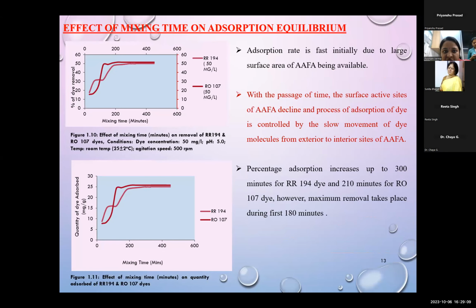Effect of mixing time on adsorption equilibrium. As we can say from both the graphs, the adsorption rate is fast initially due to the large surface area of AAFA being available. With the passage of time, the surface active sites of AAFA decline, and the process of adsorption of dye is controlled by the slow movement of dye molecules from exterior to interior sites.